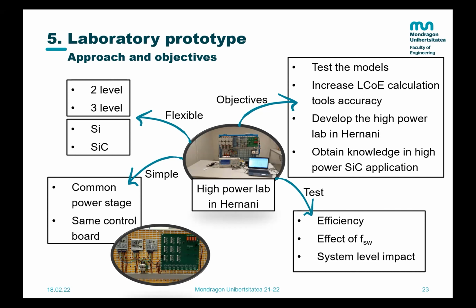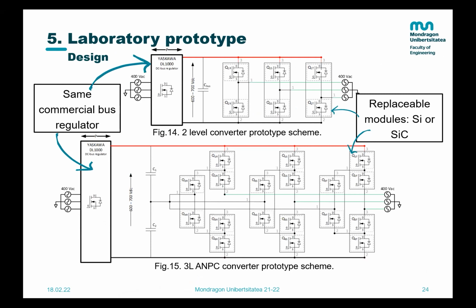For that, we wanted to test the efficiency, the effect of the switching frequency in silicon carbide modules, and overall system level impact when you introduce silicon carbide semiconductors. So the approach was to buy a commercial bus regulator, connect it to the 3-phase grid, and build a DC link. And then to that DC link, connect our prototype, the 2-level converter or the 3-level converter. The modules in these prototypes are replaceable, so we can switch easily from silicon to silicon carbide.